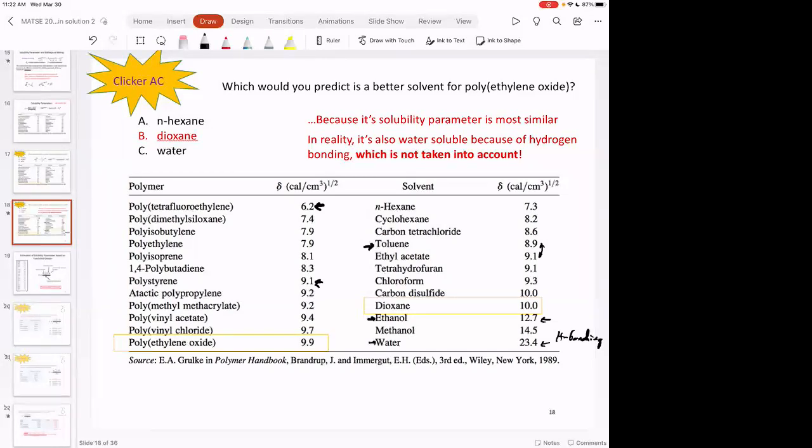We know those are miscible, but they've got 11 points different solubility parameter. We would say under usual circumstances, there's no way that's going to work. And of course it does because they hydrogen bond. So what I'm saying is that this table works for non-polar molecules, when you have dispersion interactions, things like that. It doesn't work for some exceptional cases where there's hydrogen bonding.